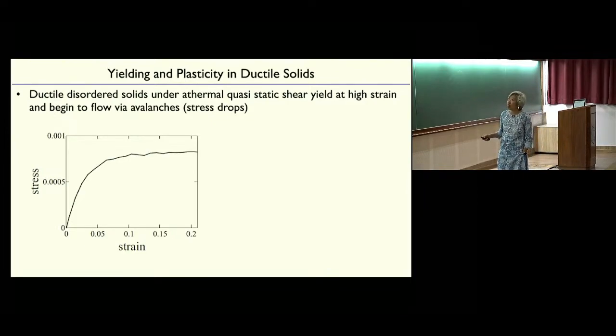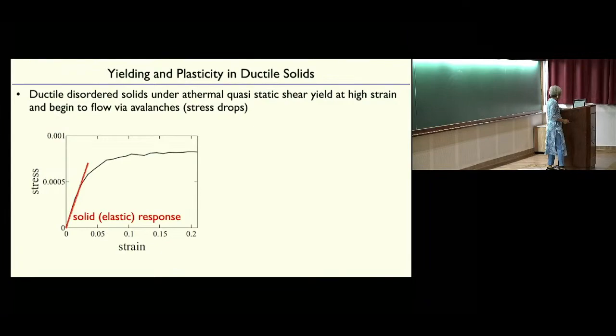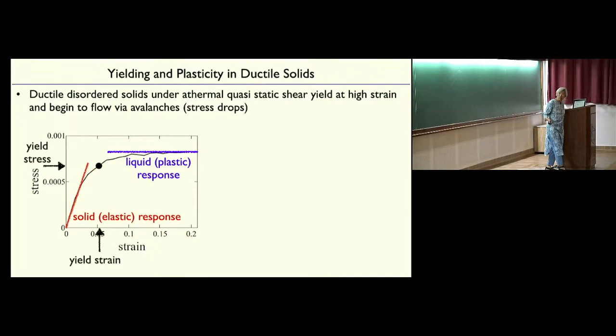Okay, if you look at the stress versus strain, what you find is that initially, right, for small strains, the stress is linear in the strain, it behaves elastically. It says, oh yeah, I'm a solid, no problem, okay? But if you put a stress that's too large or strain it too far, right, this bends over. And then it flattens out, it starts flowing, okay? So that's what it does on average. That's the solid response, and that's the liquid or plastic response. And there's a point in between, okay, where we say that's the yield stress. That's the point at which it starts to yield and starts to flow.